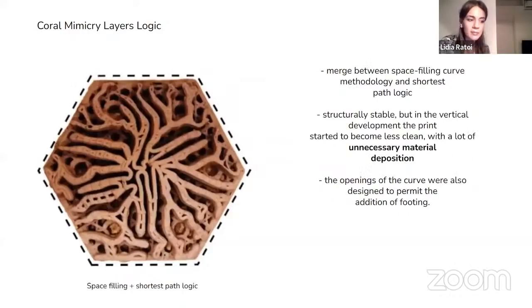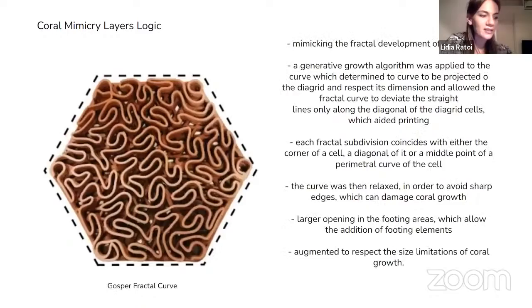Then we decided on a mix between a space filling curve logic and a shortest path. And it was drying okay, but it was using too much material. It was taking too long to print. It was taking too long to dry. So finally, we experimented with the Gosper fractal curve, and that was actually growing from the layers underneath because we were printing first the grid layers, and then on top of it, we were printing the coral mimicry layers. So they had to dry cohesively together.